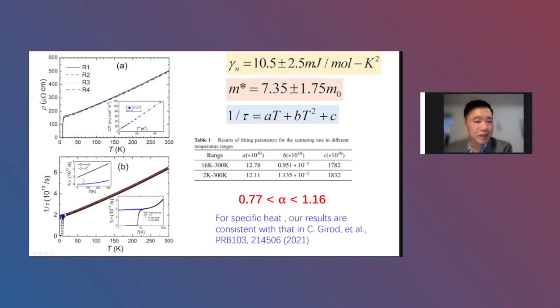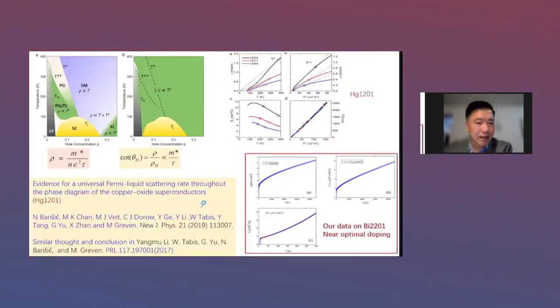So from the linear term, and from the mass and the charge carrier density, we can determine the alpha. We find it's very close to 1, you can see, okay? And actually, some groups say that in Mercury 1201, if you calculate the so-called Hall angle, which does not depend on the charge carrier density, in that case they found that it becomes the so-called Fermi liquid-like quadratic.